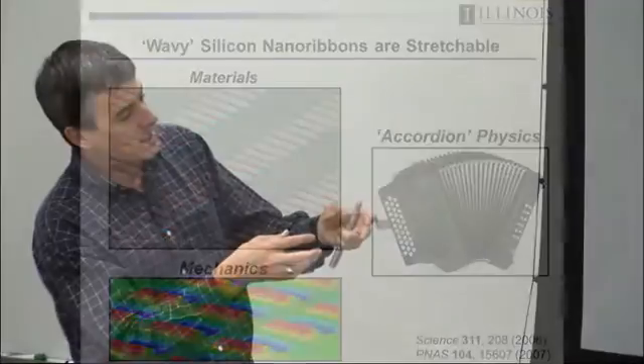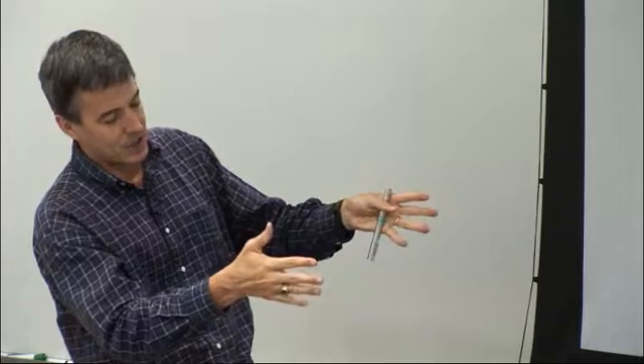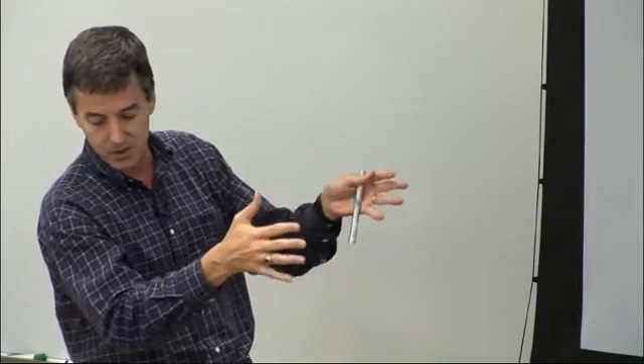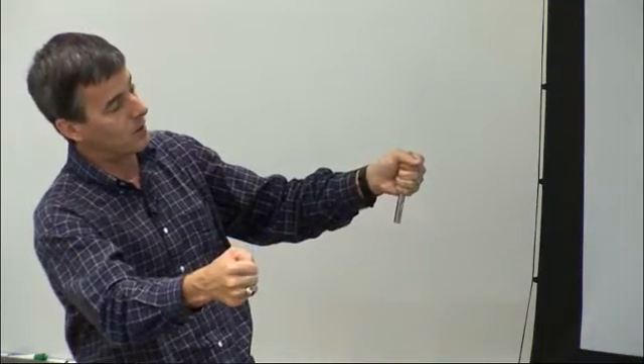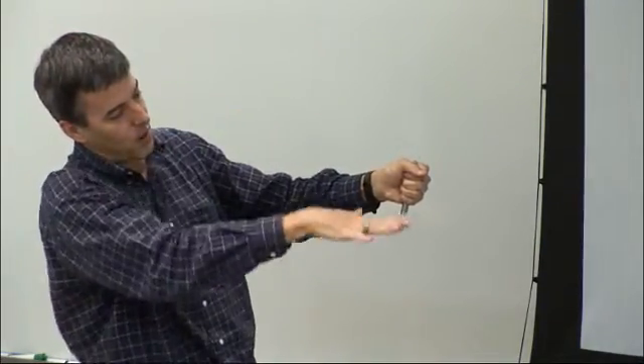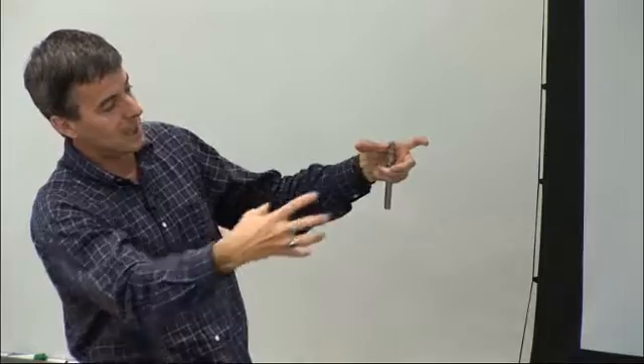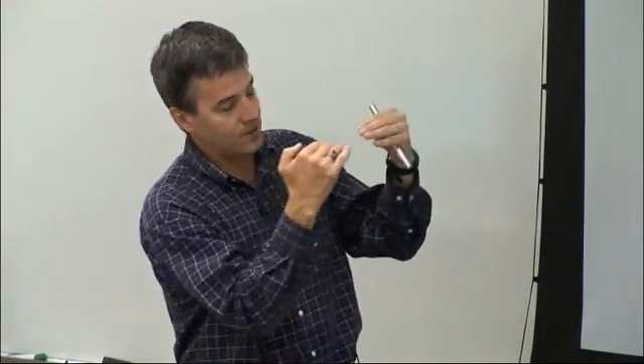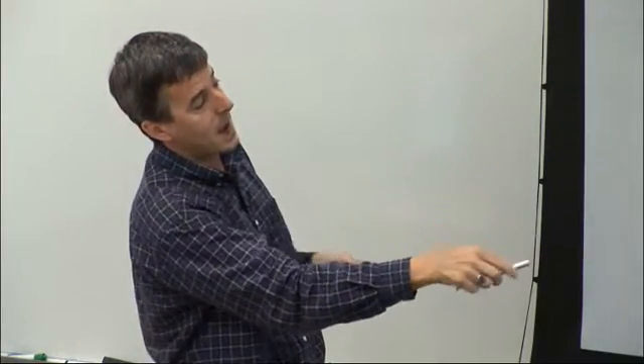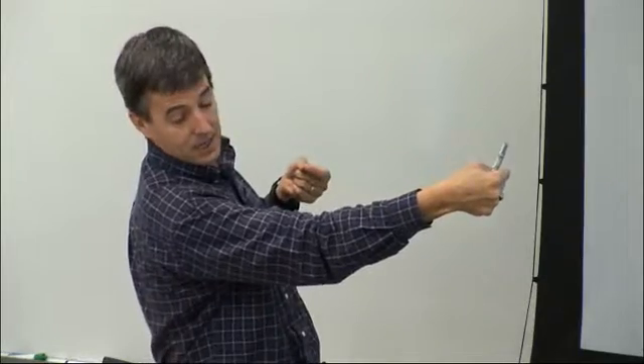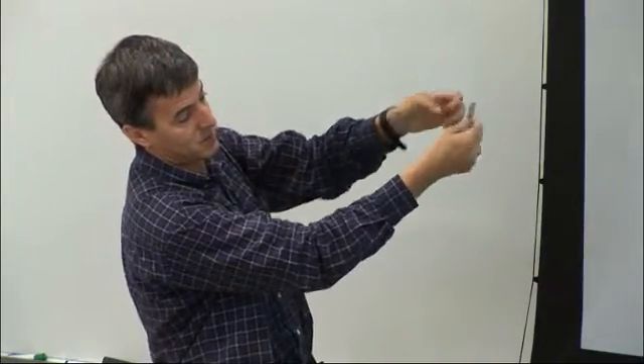So if you take this thin silicon and you bond it to your elastomer substrate, ultimately you want something that stretches, you probably need to use a stretchy substrate. So you stretch out your silicone rubber, and then you use surface chemistry such that upon contact, this silicon will bond very well at the interface with the rubber, such that when you relax the pre-strain, it induces compressive forces on the silicon. And what happens, it will cause the silicon to spontaneously buckle into that type of shape. And that's pretty nice, because it's an accordion bellows made out of silicon on silicone. And in particular, if I stretch it out now, I'm not stretching the silicon itself, but I get effective end-to-end stretchability, because I'm trading out-of-plane displacement for in-plane deformation.